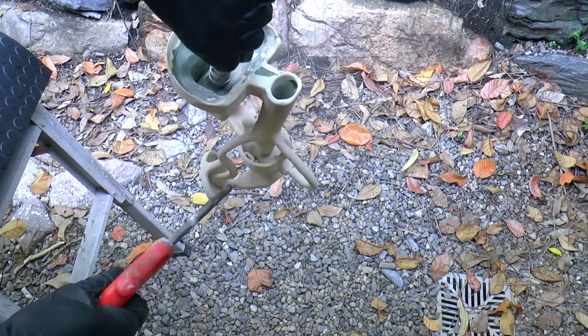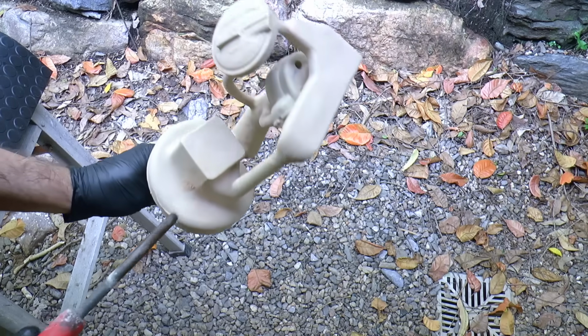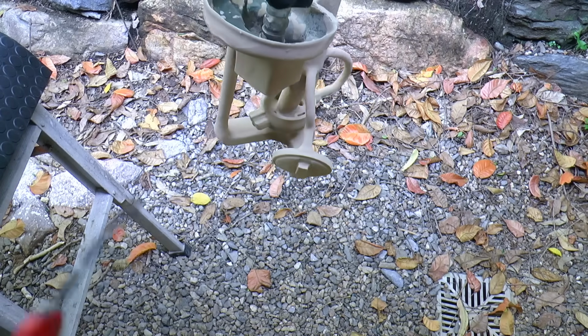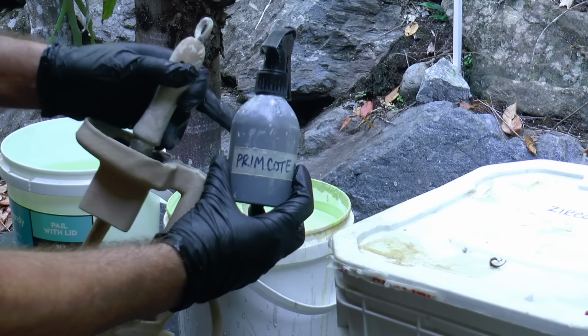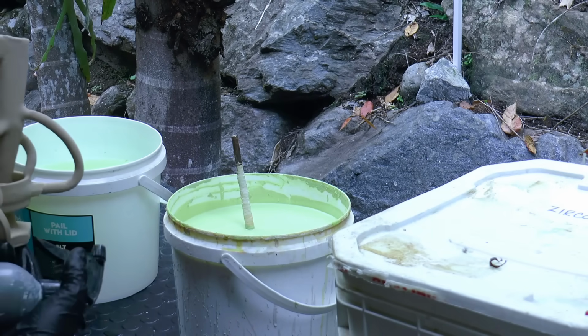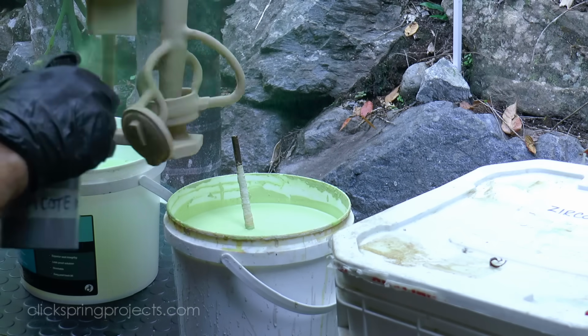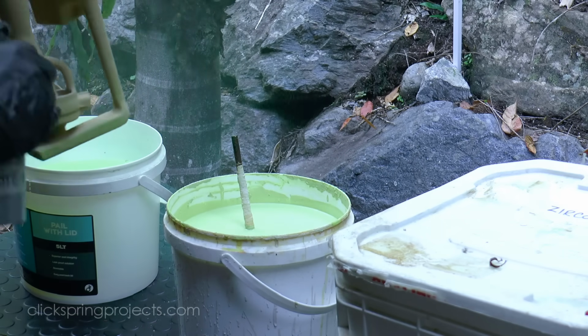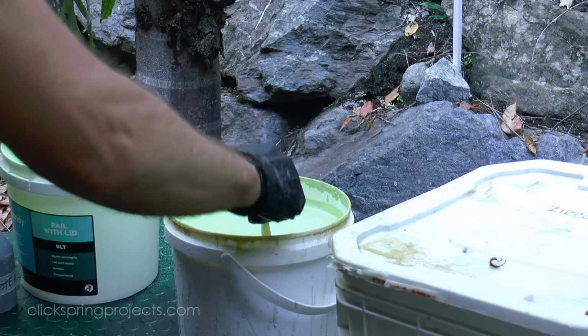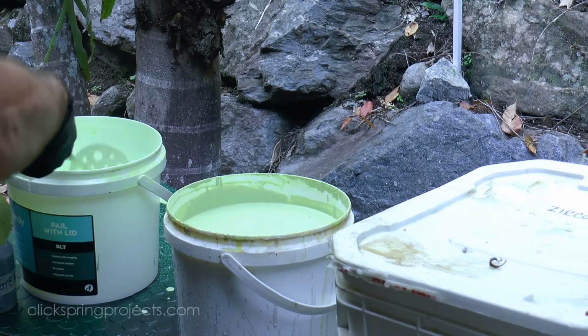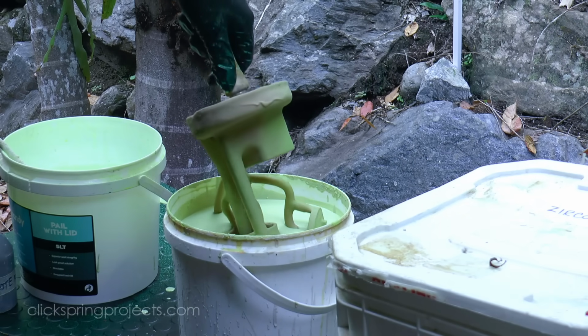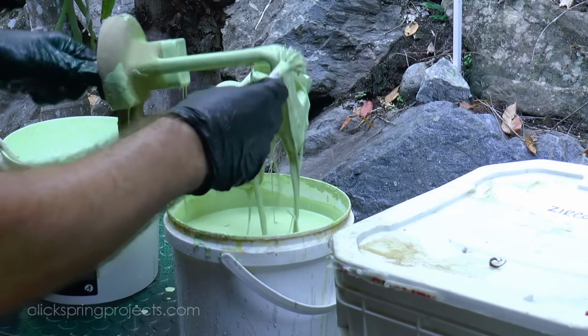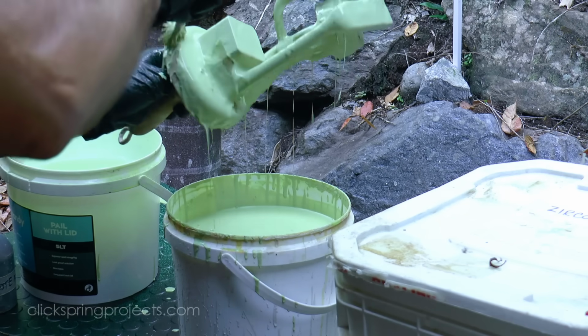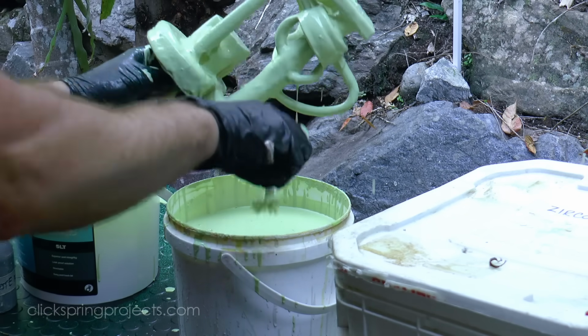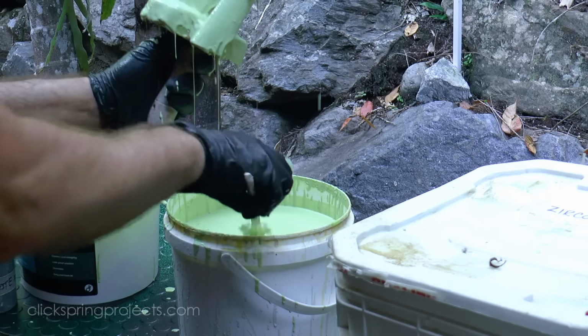In between coats, it helps to pre-wet the surface just prior to the next dip to get better adhesion between the layers. I've found simply giving a light spray coating of PrimCote works well, and it makes sure that I have no issues at all with delamination of the primary layers. Otherwise, the process is the same as the first. Dip in the slurry, wait for stability of the slurry on the pattern surface, and then dust the pattern with refractory sand.